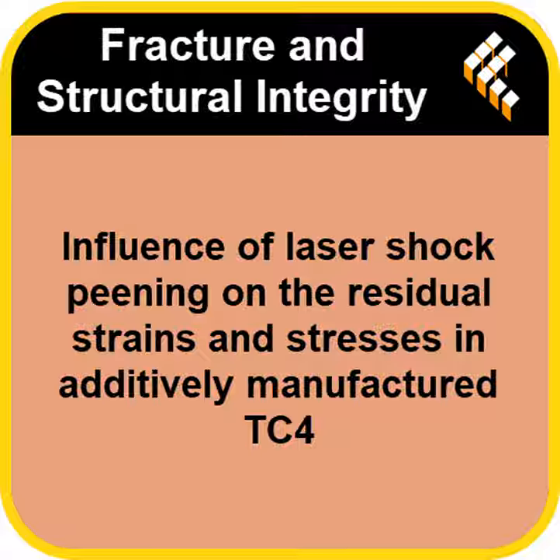And did that anisotropy, the directionality, affect the LSP results too? Like, did the laser beam shape matter differently depending on the sample orientation? It did. They tested different beam shapes, specifically a square versus a round spot. For the samples cut along the printing direction, x-axis, the square beam, a 1 by 1 millimeter square, actually produced a better result, deeper compressive stresses than a round beam.